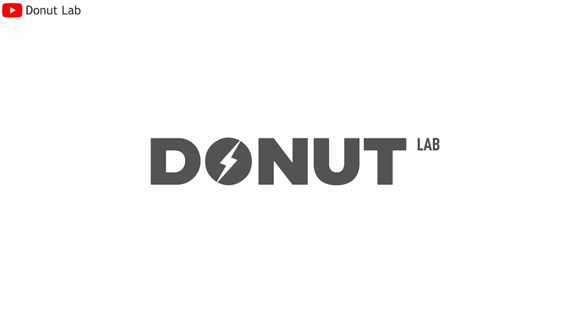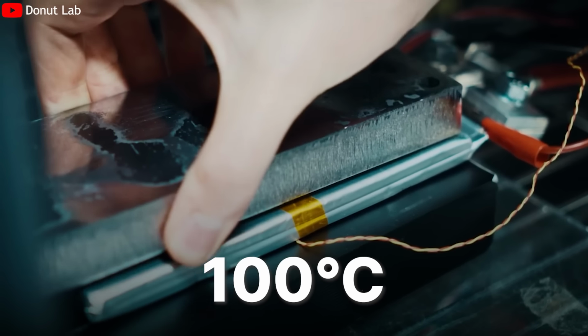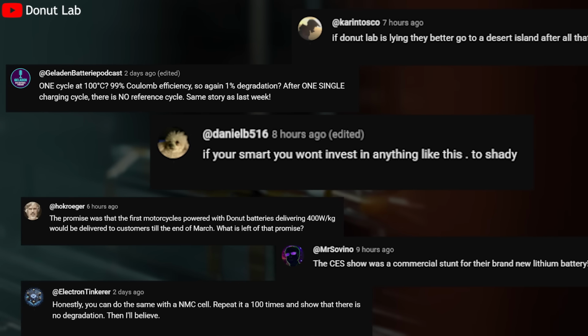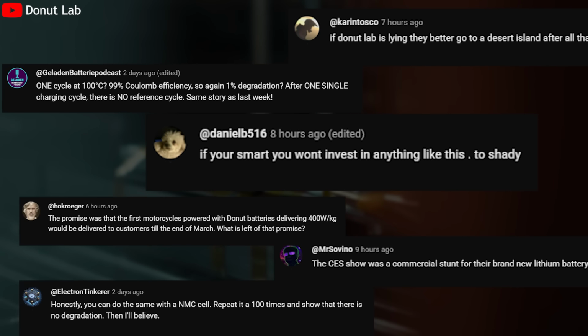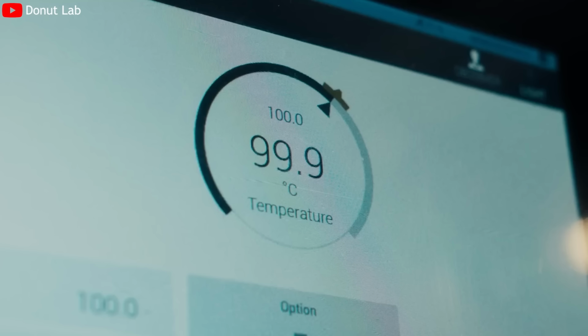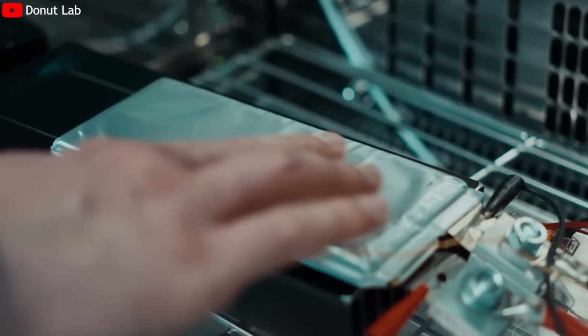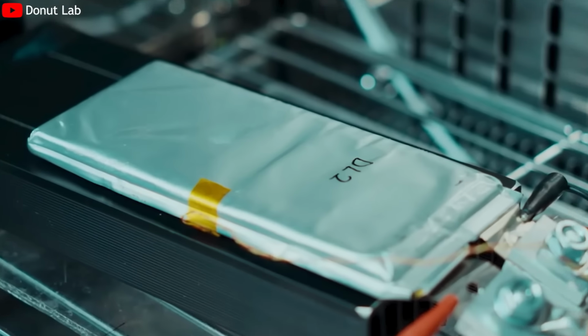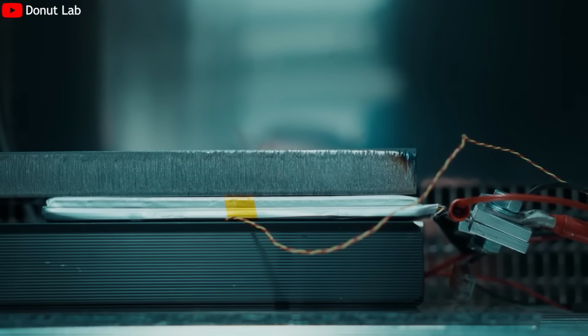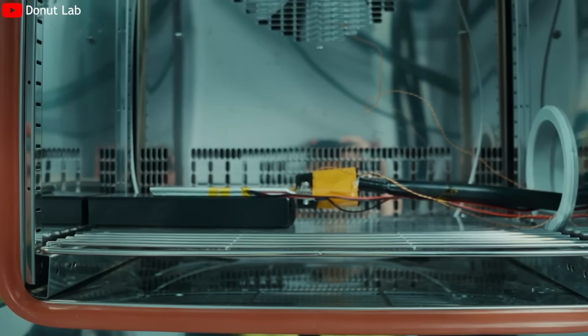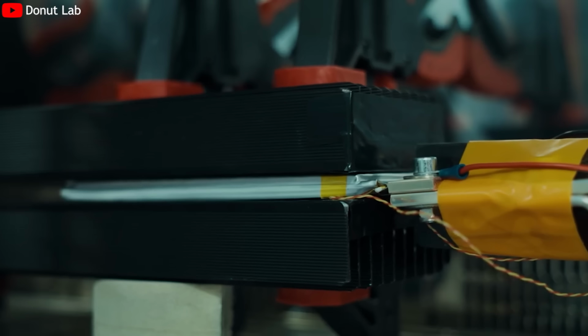...when Donut Lab released the results of their 100 degrees Celsius thermal test. Most of the conversation focused on one dramatic claim: the battery survived extreme heat. But the most important detail wasn't the temperature itself. It was the fact that the pouch seal failed. The cell visibly swelled. The internal vacuum was lost. And yet the battery continued to operate normally afterward.